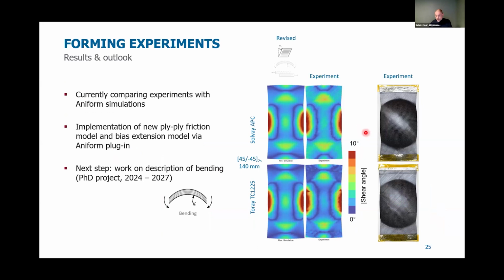And all of these experiments are being virtually repeated, so simulated with AniForm, incorporating a new description for the bias extension, for friction. You can tune other parameters as well, such as bending, adhesion, typical things that are available in AniForm. Just a small glimpse. Here we are comparing simulation to the experiment, and we see very good correlation there. We can use the AniForm plugin, a little environment where we can incorporate our own developed material models and test them before, if the interest is there from AniForm, they will implement it in a robust and industrial way.